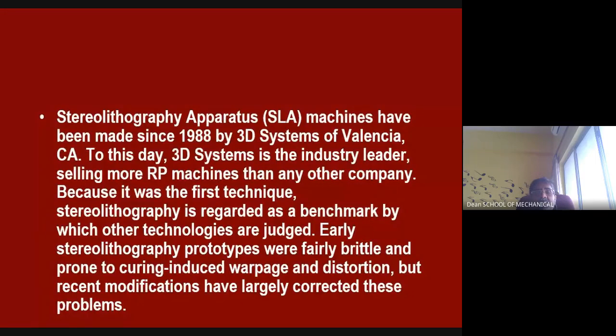Early SLA prototypes were fairly brittle and prone to curing-induced warping and distortion. In the early stage, the SLA process faced some quality issues, like the prototypes being fairly brittle and prone to curing-induced warping and distortion. But recent modifications have largely corrected these issues. Nowadays, these issues are sorted out in SLA.